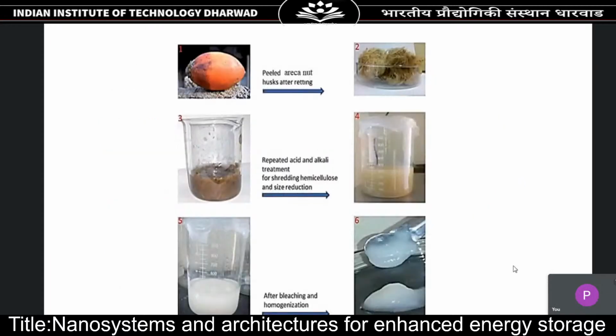So this was the method for getting the nanocellulose from the areca nut. You take the areca nut, you peel it, and then you do repeated acid and alkali treatment with HCl and NaOH. So you can shred the hemicellulose and you can also reduce the size. Then you carry out bleaching and homogenization. Bleaching was carried out using sodium hypochlorite, and then we also used acetic acid. After the homogenization, we could get a stable sol.